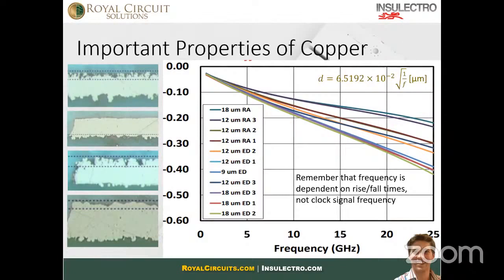So looking at this, I'm trying to make sense of those two colors. It looks like 18 micrometer rolled annealed and rolled annealed 3. So in this case, we're just looking at the thickness of the copper, not so much the distance between the peaks and valleys of the copper. That's what that equation is up on the top right-hand side. I think, Mark, you added that in there. And in this case, we're just looking at different thicknesses.